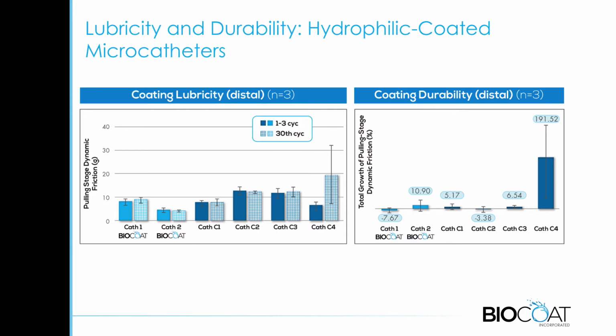So the other thing we did was look at the various hydrophilic coatings. And we did this by actually purchasing neurovascular microcatheters from the manufacturers. Two of them actually had Biocoat coatings on them. The other four had other hydrophilic coatings. And so again, we looked at these from the lubricity, the durability, and the particulates.